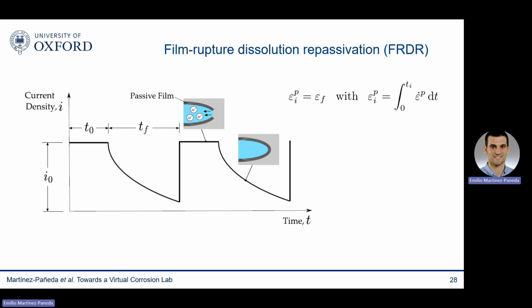The other way in which mechanics typically impacts corrosion is by disrupting the passive layer, of course. And as you know, this is a cyclic process. You form a passive layer, which is becoming more stable with time. So then you reduce the corrosion current density. But then when your strains are large enough, then you fracture the passivation layer, and that leads to a sharp increase in corrosion current density.